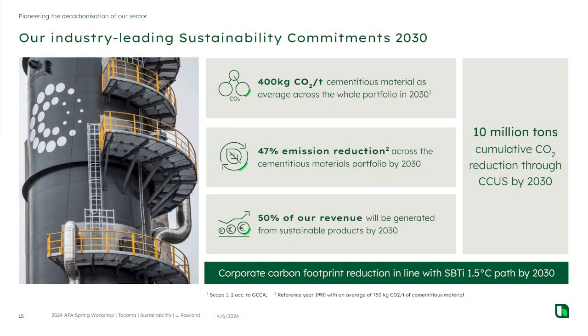And one of these goals is to reduce our cementitious materials down so that we are only producing 400 kilograms of CO2 per ton of cementitious material. So essentially what that means is, don't get hung up on metric versus imperial units. Pound for pound, standard Portland cement has about 0.9 pounds of CO2 associated with every pound of cement. We're trying to get that down to 0.4, right? So 400 kg per metric ton's 1,000 kg, simple math. That's why I like to keep it in metric. All right, so that's a big ambitious goal.